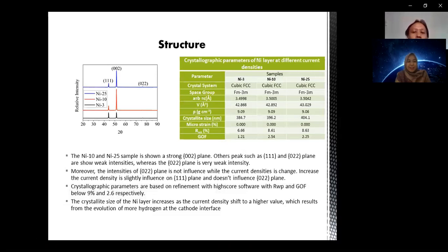The 022 plane has very weak intensity, and its intensity is not influenced when the current density is changed. Increasing the current density slightly influences the 111 plane and doesn't influence the 022 plane. The crystallographic parameters are well refined with high scores, with Rwp and GOF below 9% and 2.6 respectively.